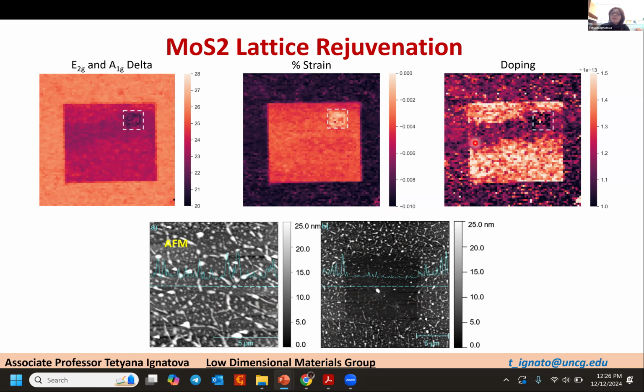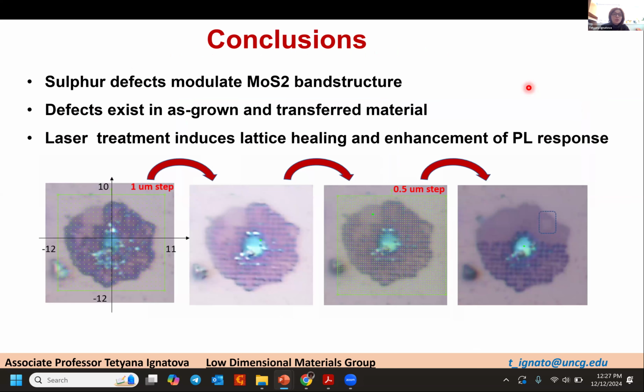For this particular picture, there is, I don't know, probably some crack coming through the sample. This is the explanation of this line. But we can also see and calculate how much doping we introduce just by irradiating the sample with a certain laser power. And I think I'm very short because I can now jump to my conclusions: we see that sulfur defects modulate the molybdenum disulfide band structure, and we see that defects exist in as-grown MoS2 and transferred material. And we see that laser treatment induces lattice healing and enhanced photoluminescence response.